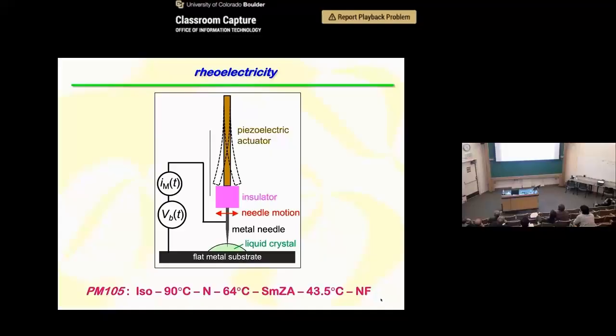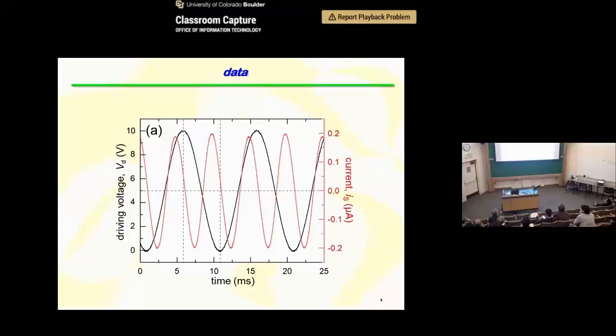Well, so we have some cool experiments. You have a flat metal plate, you put a drop of liquid crystal, you stick a needle in it, and then you vibrate the needle. Okay, and then you have an electrical circuit: the needle, something to measure the current, the bias voltage, and the substrate, so that we are measuring the induced current. You get a very nice, nonlinear response, a nice second harmonic response that depends on the bias voltage.